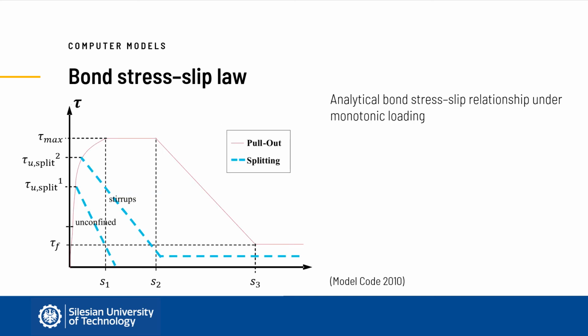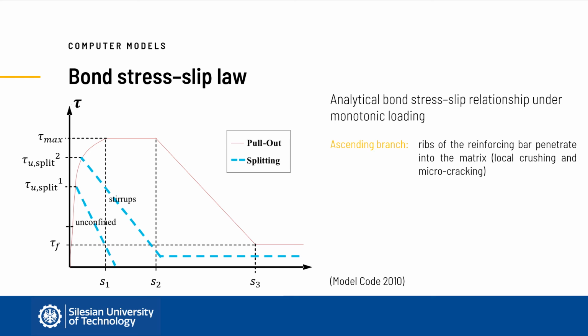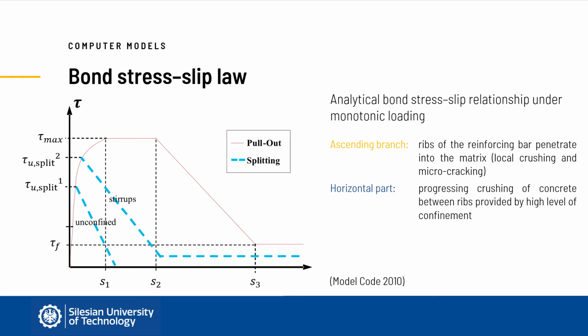Consequently, the bond-slip law has the following form. The first curved part refers to the stage in which the ribs penetrate into the mortar matrix. It is characterized by local crushing and microcracking. In case of unconfined concrete, splitting failure occurs, which is reflected by a sudden drop of the bond strength. The horizontal level occurs only for confined concrete. It reflects advanced crushing and shearing off of the concrete between the ribs of the bar. This level represents a residual bond capacity, which is maintained by large concrete cover or transverse reinforcement, keeping a certain degree of integrity intact. The decreasing branch refers to the reduction of bond resistance due to shearing of the concrete corbels between the ribs.